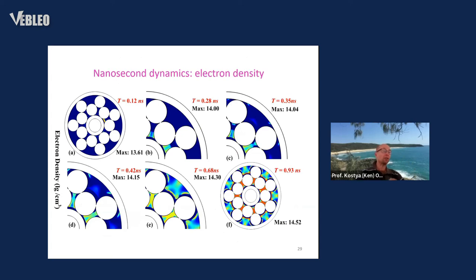What happens is that the catalytic beads interact with the plasma, and the electric charge is distributed on them, and they facilitate the generation of electric gas discharges in those small spaces, typically sub-millimeter and even micrometer spaces between those catalytic beads. Plasma is generated, and the density of plasma increases with time. And as the plasma density increases with time, it becomes more effective in interaction with the gas that we are trying to reform and generating the products of the reaction.